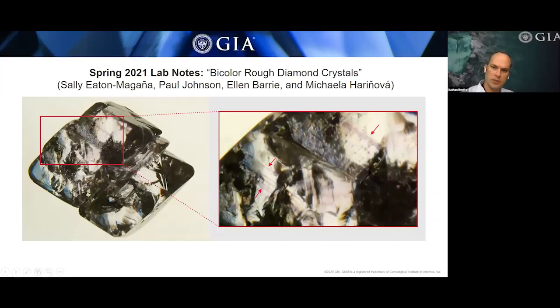And in one of the crystals, you can see that there are these strong pink graining lines resulting from significant strain that the diamond would have undergone while it was in the ground. However, that pink graining does not continue on to the other diamond crystal. So that suggests that the pink diamond crystal underwent some strain, and then the second adjoining crystal was overgrown or grown attached to the crystal at a later time. And so it was not subjected to the same kind of strain.